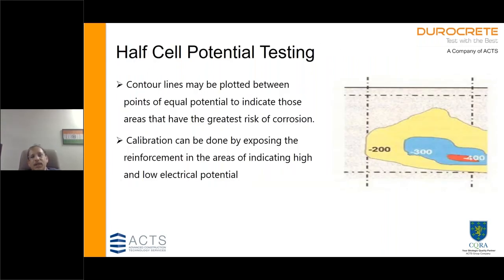When you have a structure that is distressed, you can identify areas that are not showing visible distress, but are likely to have corrosion started inside. And it is advisable that when you do this testing, you should calibrate it by exposing certain areas. Certain rebars need to be exposed, and you need to calibrate the potential difference against how the bar actually looks, how much corrosion has happened.